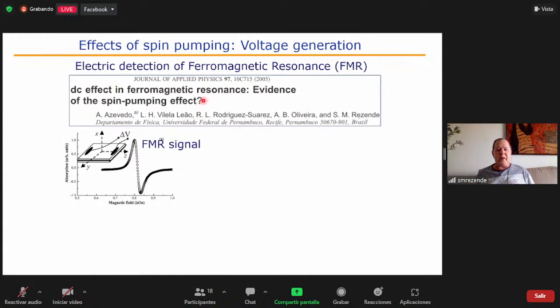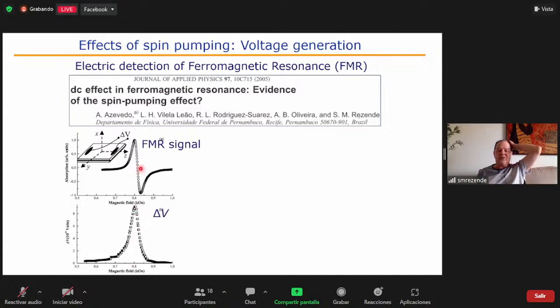What is the experiment? The experiment was done with a trilayer, two magnetic layers with a non-magnetic layer between them. And then Antônio had the idea of putting two contacts at the ends of these structures, with a few millimeters of dimension. And this is the FMR signal that I showed before. Now, by measuring the voltage between the two contacts, they measured, I say they because I was in Brazil at that time, just following their work. I was not so much involved. I only participated in some discussions. But the voltage gave this incredible result: a Lorentzian line at the same field as the resonance.